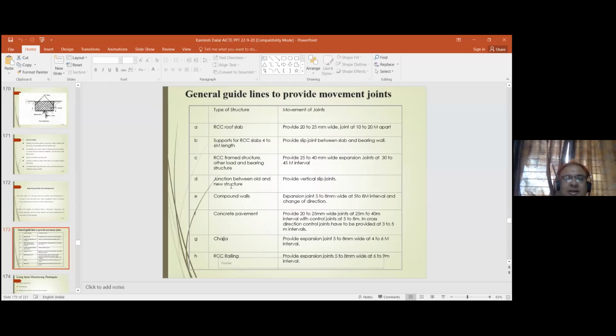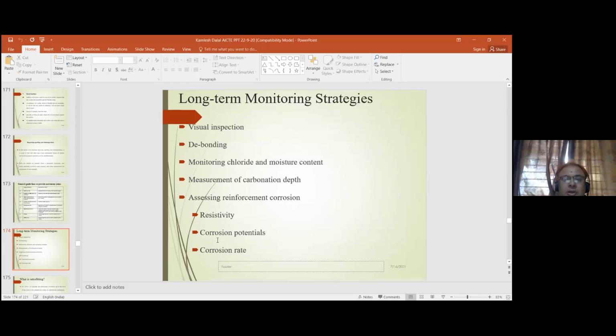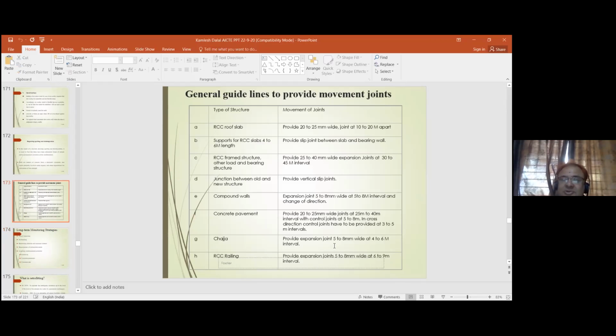In an RCC frame structure like this, at the junction of old and new structure, provide a vertical slip joint. In a compound wall, an expansion joint 5 to 8 mm wide at 5 to 8 meters. If it is not provided, cracks will be there. In a concrete pavement also, a 20 to 25 mm wide joint at 25 to 40 meters. In a chhajja also, provide an expansion joint 5 to 8 mm wide at 4 to 6 meter interval. And in RCC railing, provide an expansion joint 5 to 8 mm wide at 6 to 9 meter interval.